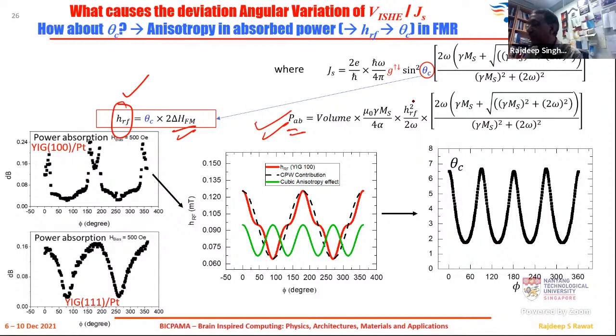And because the power absorption has this h_rf dependence, we experimentally measured the power that is absorbed in our system. So this is the power that is absorbed in the system, power absorption for the YIG 100. And from there, we actually calculated how h_rf is varying. And you can see the power absorption for the 001 is different from that for the 111. 111 still shows, you can say, two-fold symmetry, but this does not show two-fold symmetry. This itself is quite complicated.